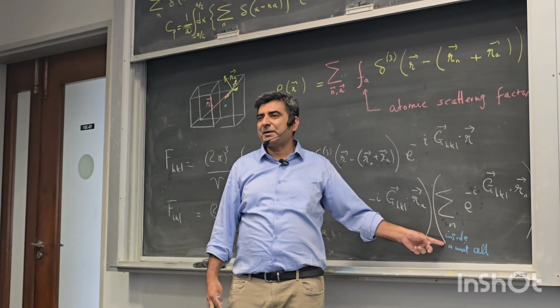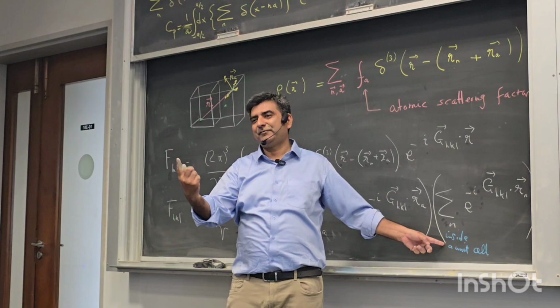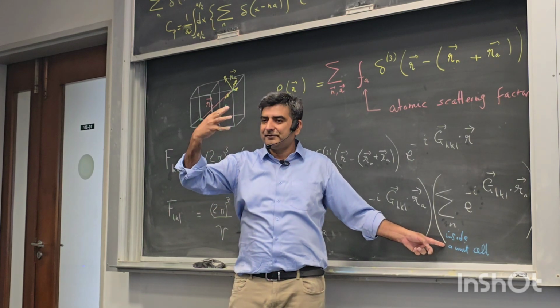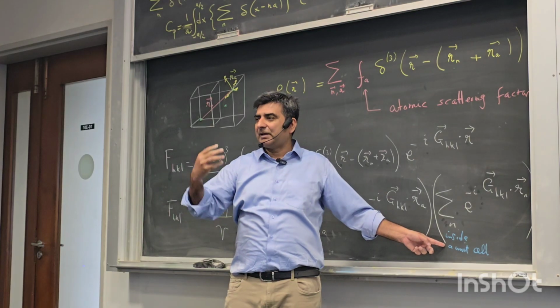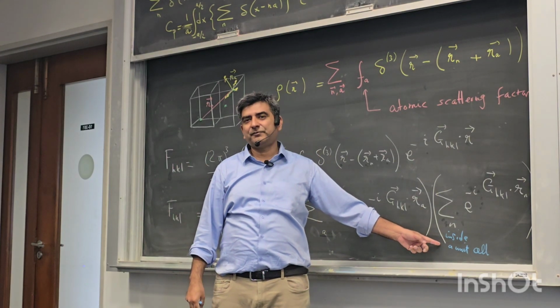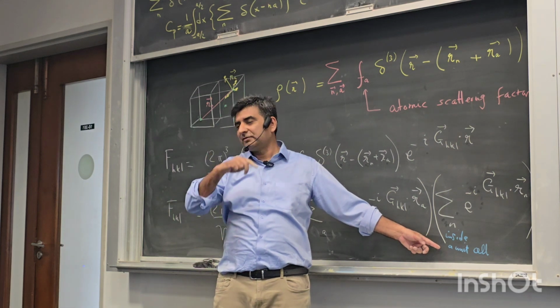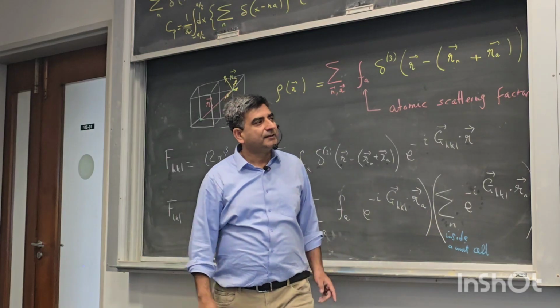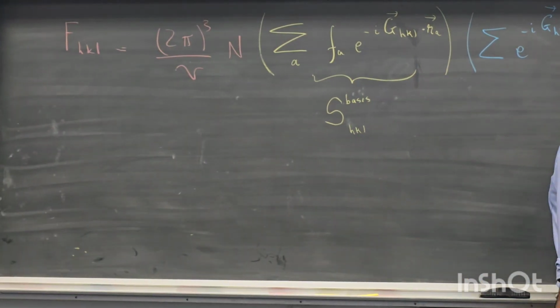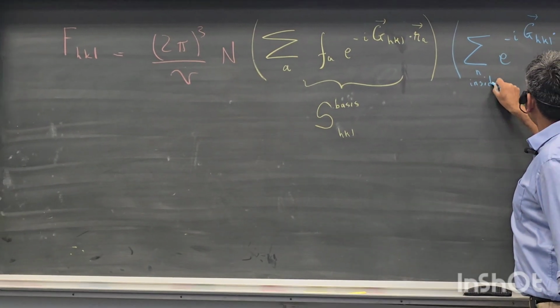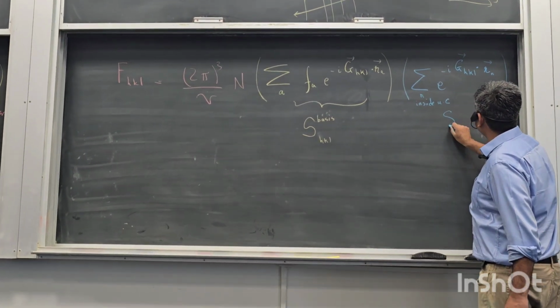Alright? So for a primitive, there is only one point in a lattice cell. For a body centered, there are two. For a face centered, there are four. For a base centered, there are two. So you just have 1, 2, or 4 points to be considered for different kinds of Bravais lattices. So this is due to the lattice. This factor is due to the lattice. This is n inside the unit cell. So this is due to the lattice solely.